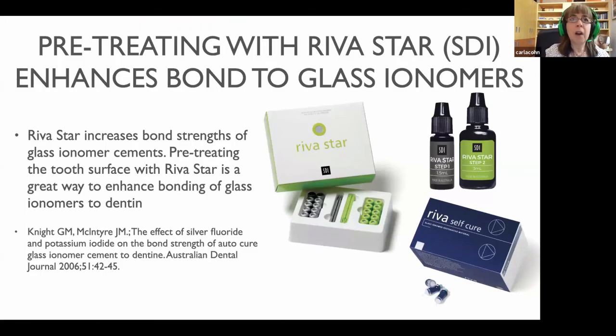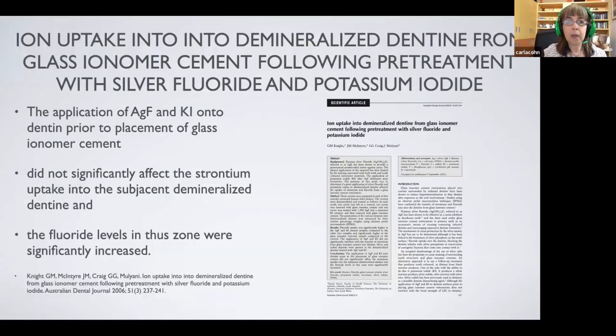Pre-treating with Riva Star for our use of glass ionomer is actually going to enhance the bond of glass ionomer to our tooth surface, and so it's a great way to enhance that bond. Regarding ion uptake into demineralized dentin from glass ionomer cement following pretreatment with silver fluoride and potassium iodide, we see fluoride levels in the zone significantly increased. We see not a significant effect on the strontium uptake into subjacent demineralized dentin.